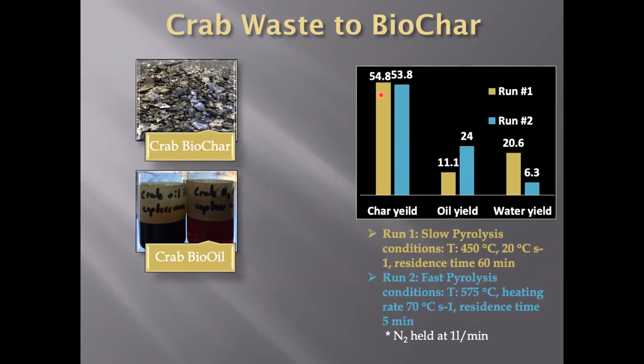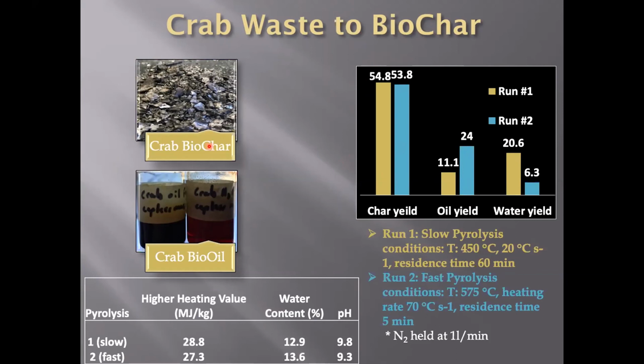So we're getting about 50 to 55% crab biochar through pyrolysis. But depending on if we use fast or slow pyrolysis, we'll get either a higher bio-oil yield or a higher water yield. So fast pyrolysis gives us higher bio-oil yields, and slow will give us higher water yields. As I said, we haven't done a whole lot of work with the crab bio-oil that's produced so far, but what we have started looking at is whether it could possibly be used as a replacement biofuel.